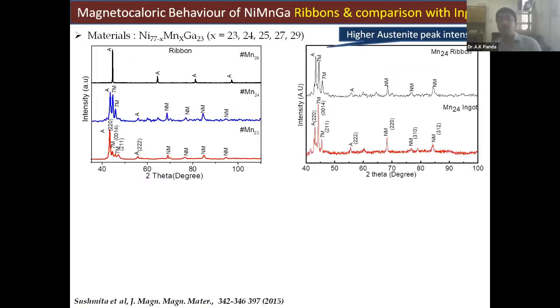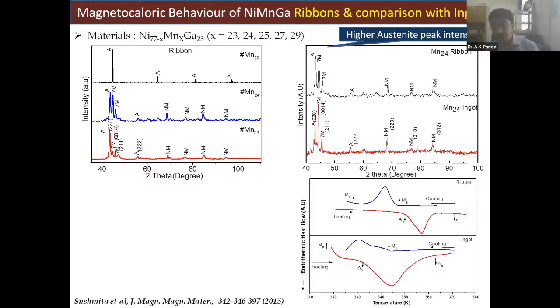So this is when we compare the ribbon and ingot with the manganese 24 concentration. You find that there is a lot of difference actually. You have a lot of non-modulated martensite and emergence of the austenite here. And this is for the ribbon and ingot.